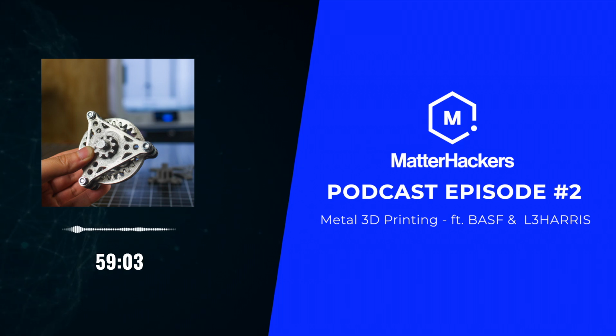You can't use support material, so anything that would require support material to print is not going to come out successful from the debinding and sintering. So you just have to pay attention to your overhangs, your overhang angles, and wall thicknesses too. And with that, anything that you can do to give yourself a little overhead from the recommended minimums is going to go a long way.